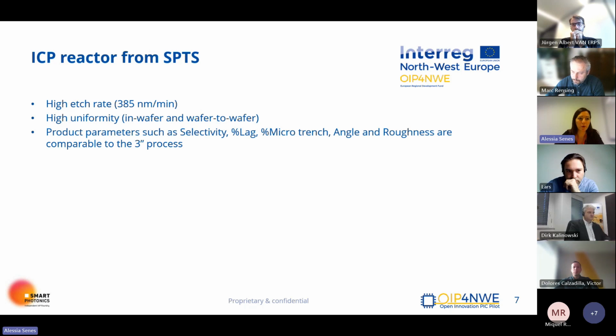The third tool that has been bought and installed in the project is the ICP reactor from SPTS. Also here we can achieve a high etch rate. We use up to 385 nanometers per minute. This reactor allows for high uniformity in wafer and wafer to wafer, and the process parameters such as selectivity, percentage lag, micro trench, angle and roughness are comparable to the 3-inch process and are all in spec.